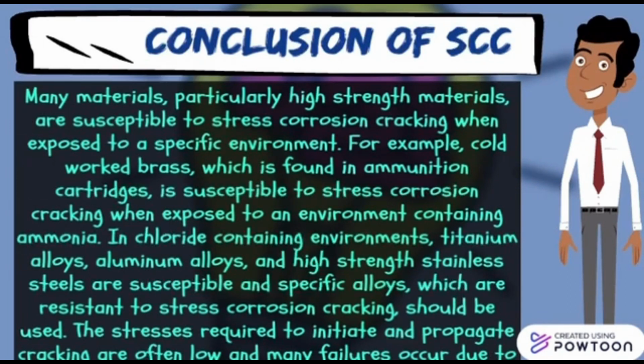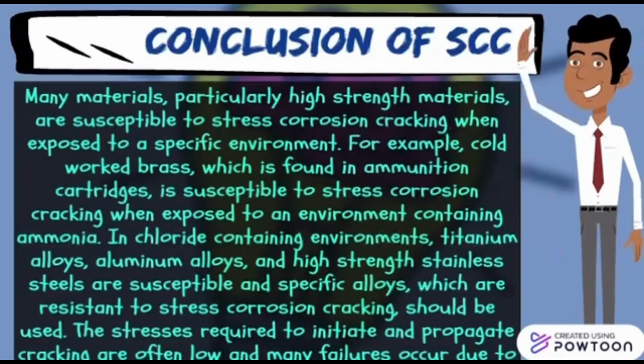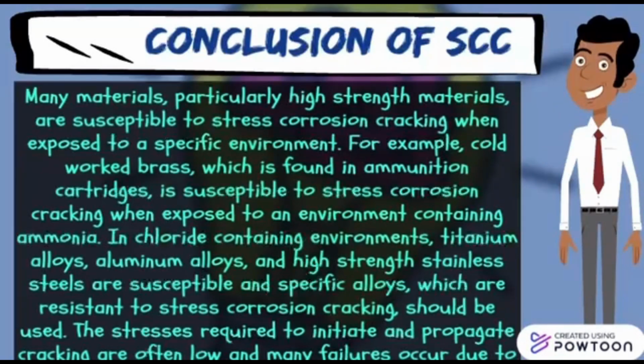The conclusion on SCC is that many materials, particularly high-strength materials, are susceptible to stress corrosion cracking when exposed to a specific environment. For example, cold worked brass, which is found in ammunition cartridges, is susceptible to stress corrosion cracking when exposed to an environment containing ammonia. In chloride-containing environments, titanium alloys, aluminum alloys, and high-strength stainless steel are susceptible, and specified alloys which are resistant to stress corrosion cracking should be used.